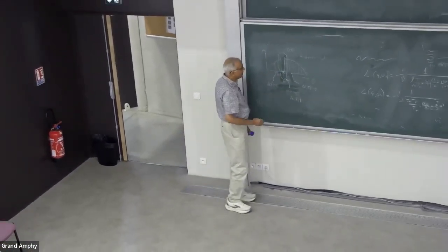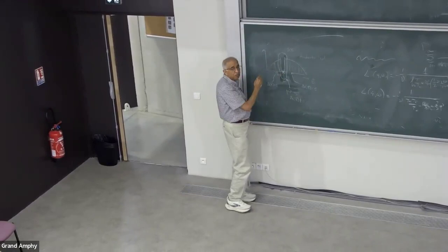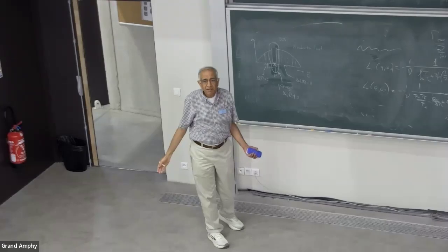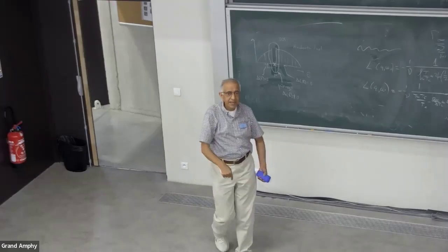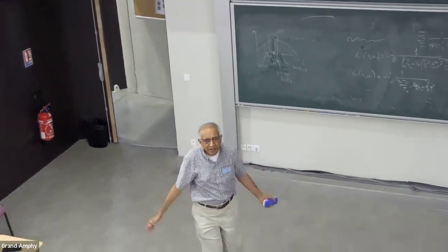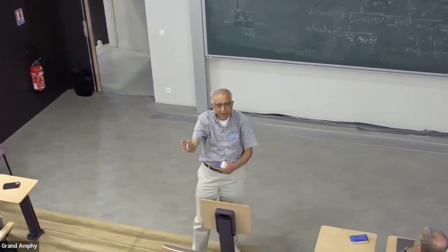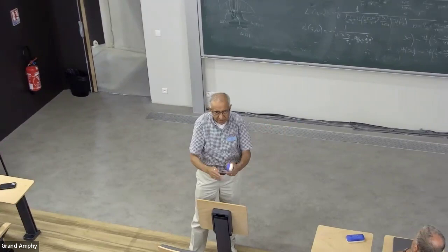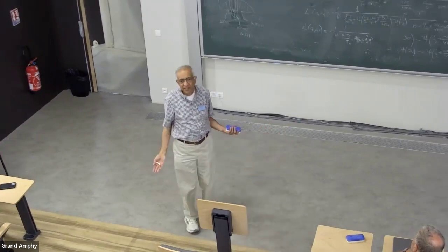Where there is no pairing, you feel that there is a huge gap locally because you're very far from the chemical potential. If you look at that state, it's living very far from the chemical potential, so there's nothing at the chemical potential. See, tunneling density of states has a wave function squared times delta function summed over all n. With me? So that's one.